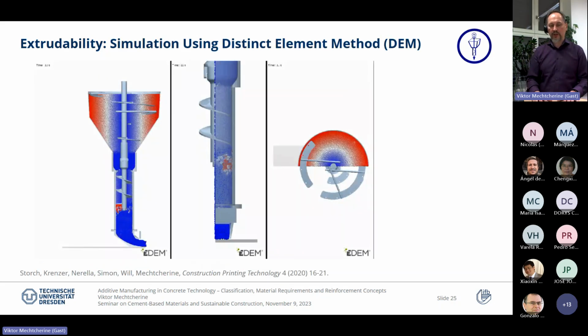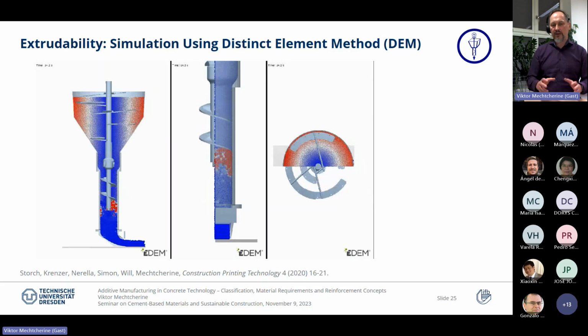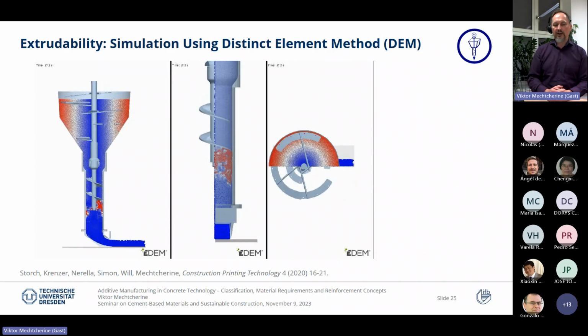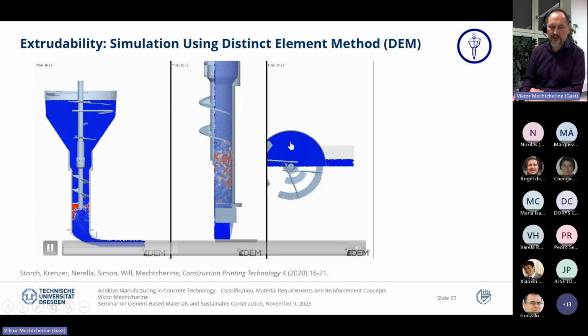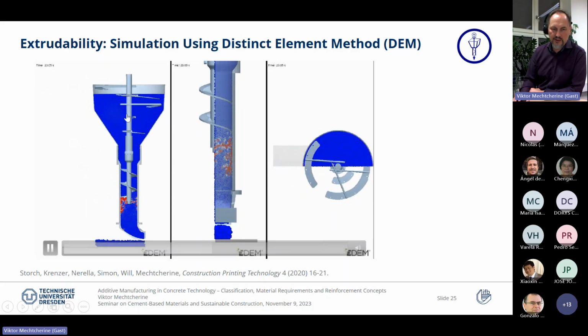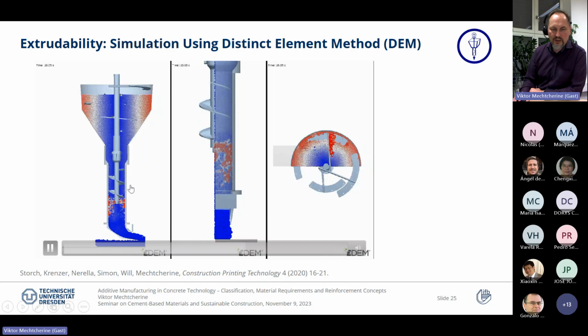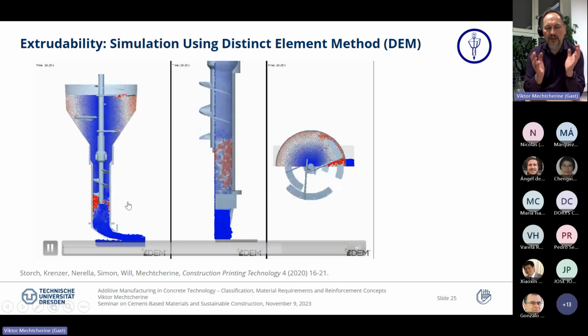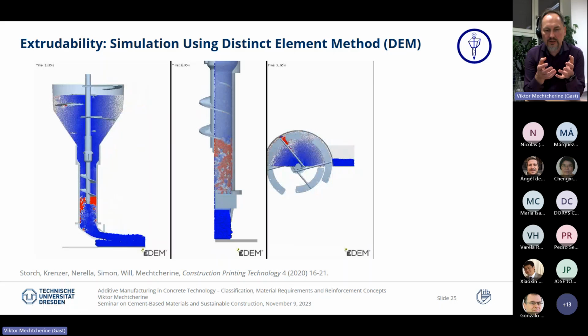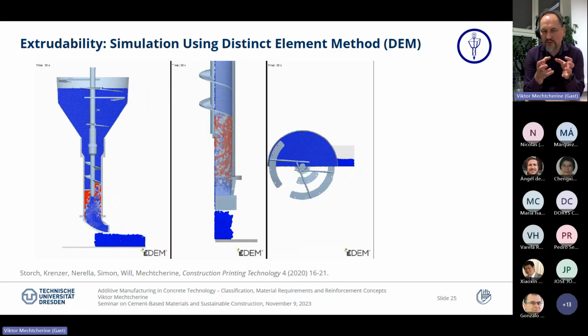But what we can do is some numerical simulation. In this case, it's using the distinct element method. And what you see here very nicely is that indeed it works. So we can process the material and deposit it. We can also get an impression of how the tool we use in the printhead to deliver the material actually interacts with the material. So this is a very feasible approach, also to improve the designs of the printheads and also some other equipment needed for 3D printing.